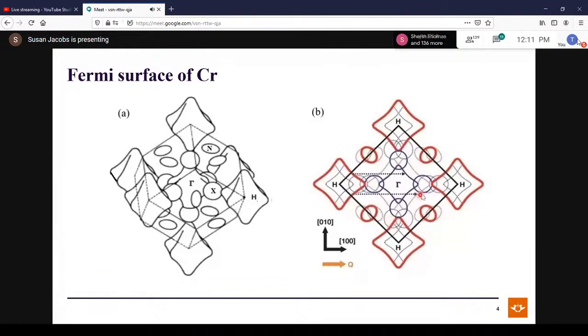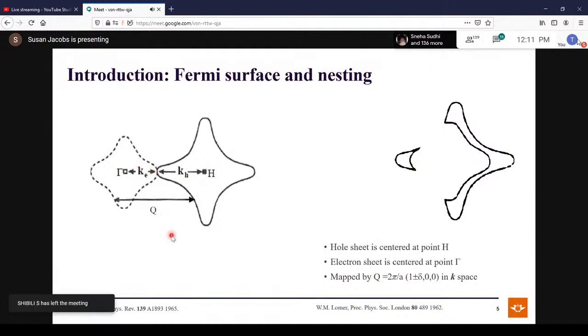Again, the dark line represents the boundary of the first Brillouin zone, and the dotted lines represent the translation vectors for the hole and electron octahedra. Okay, so what happens is, for the formation of spin density wave, a process called nesting occurs. In pure chromium, the electron sheet is slightly smaller than the hole sheet. In the process of nesting, the electron sheet is translated onto the hole sheet through a translation vector Q, the magnitude of which is given by 2π/a (1 ± δ, 0, 0), and it is in k-space. So this Q represents the distance between the electron and hole sheets in reciprocal space.